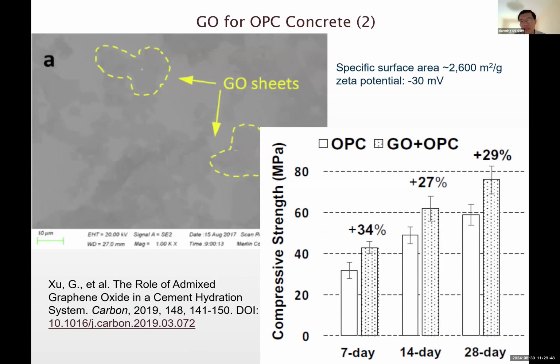earlier I mentioned the specific surface area, but look at this one. If we go by the same unit, square meter per kilogram, then we're talking about 2.6 million, which is even higher than that 1 million number we mentioned earlier on the graph. And the zeta potential is another parameter to watch out for, because not all graphene oxides are made the same. So the amount of negatively charged groups on the surface is typically measured by zeta potential at a neutral pH. In this case, a zeta potential of minus 30 millivolts indicates this is a somewhat stable system, and it's about 1 nanoplatelet, instead of multiple. Because when you have more than 5 nanoplatelets sticking together, then that graphene oxide is not very useful. It's more like a micromaterial than a nanomaterial, because it loses its magic once you have more than 5 nanoplatelets sticking together.